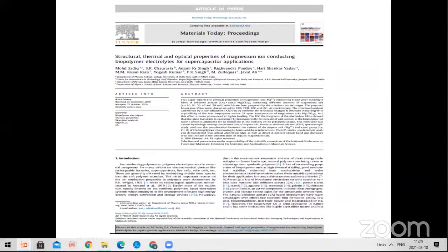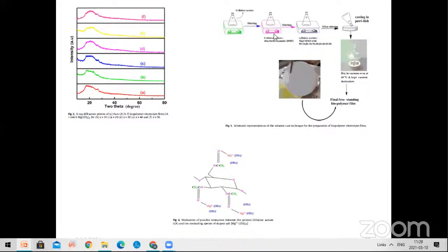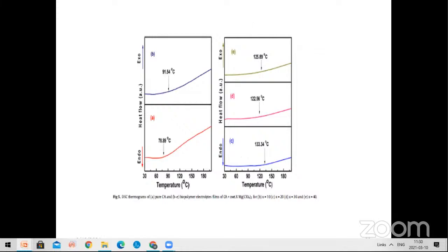And in one more study, we also check biopolymer based electrolytes. In the biopolymer based electrolyte, we take cellulose acetate as the biopolymer and magnesium as an inorganic salt. And we take different concentrations of the magnesium salt as well as the biopolymer cellulose acetate. In a similar way, we use the solution cast technique for the preparation. Finally, we got freestanding films, and then we check whether these films can be used for energy storage device applications. And also we check the thermal analysis of the biopolymer electrolytes.